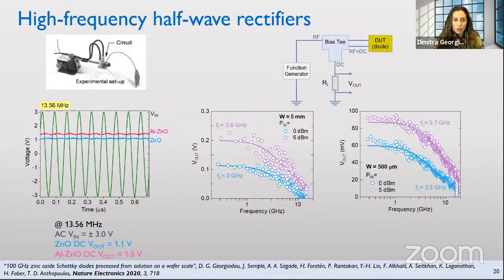To see now how our diodes would perform under an AC field in a more, let's say, real life setup, we initially fabricated this rectifier circuit you can see here, which comprises a resistor and a capacitor on the probe that was used to apply the voltage on our diodes. We saw that by applying an AC field of plus minus 3 volts at a frequency of 13.56 megahertz, a frequency which, as I explained initially, has a high commercial value. It's used in NFC tags and RFID tags in contactless cards and so on. We see that in that case, we got an output voltage of 1.1 volts for the zinc oxide and 1.5 volts for the aluminum-doped